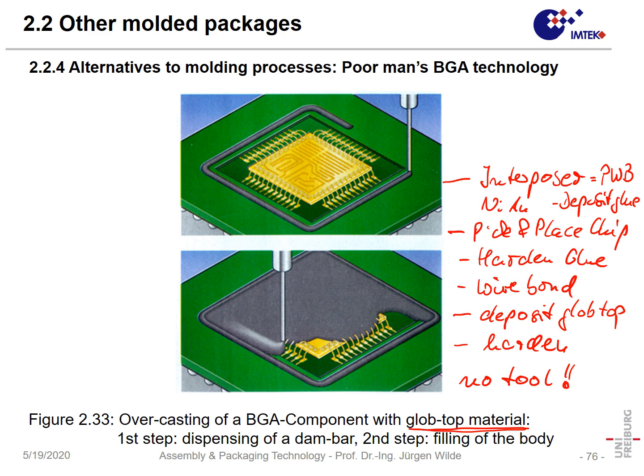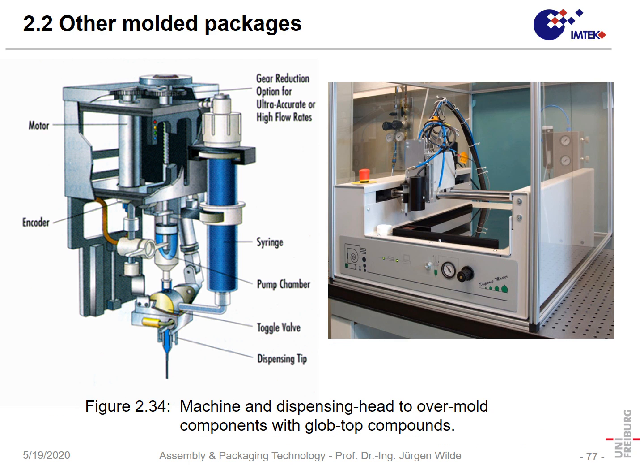Yeah, why is it so? That machine we use for deposition can be some kind of automated machine. Here we see the syringe. Here is our vision system. That's a camera and illumination in order for the system to detect where the proper position of deposition is. That complete system is programmed from a personal computer. Here we see such a deposition head for this pasty material, and this moves zigzag over our chip, and in that way we can do a coating.